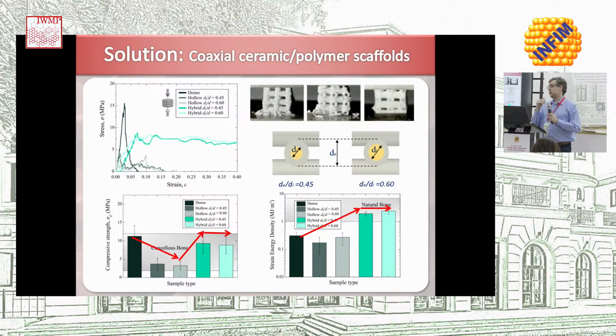So the advice would be, okay, put some polymer inside, but not too much, just enough to have the mechanical enhancement in terms of having these polymeric fibers joining together the struts even after they fail. So a small amount of polymer inside the struts is enough to get what you want.